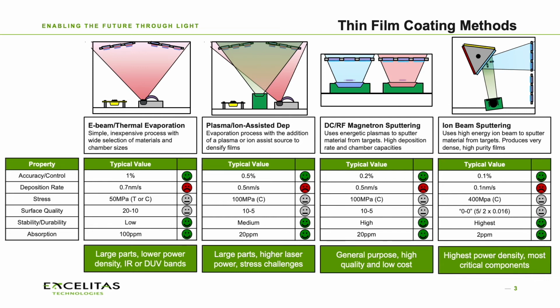One of the things that we often do to try to improve that while maintaining a lot of those benefits is add some kind of ion assist or plasma assist into that process, and that just amounts to putting a particular kind of ion source, plasma source, into the chamber and adding some energy into the deposition process. This can improve the film quality, the density of the films, the durability of the films. It also improves the consistency and thus the accuracy and control of the process. It can reduce the absorption significantly so that we can get down into the sort of 20 ppm level. And that can be favorable for certain applications, and particularly if we're trying to get better films on larger substrates. This is typically one of the processes that will apply to that.